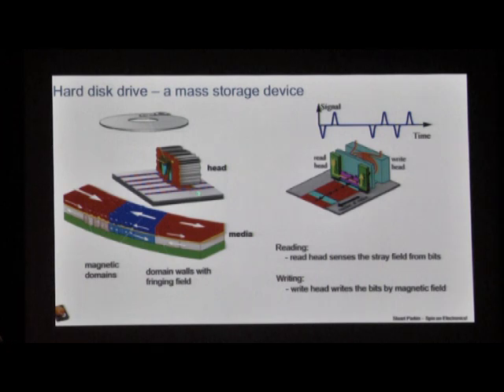And we detect these fringing fields by their change in the resistance of this spin valve engineered structure, which we can deposit on the back side of a small ceramic object, the recording head, which today is riding above this glass disc at a separation of only 1 nanometer during the reading and writing process. So it's an amazing technology that works even though it's mechanical and involves a large object, the disk in which we store this information.